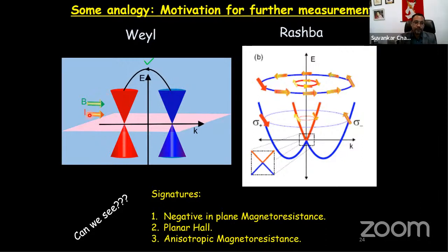And when you change the angle between the current direction and magnetic field, the magnetoresistance amount changes similarly. Now, if you think of Rashba, I don't want to say they are exactly the same, but the similarity is that here also you have two types of spin chirality, but instead of having two Dirac cones, it is circulated by one Dirac cone. So the signatures of Weyl fermions, or Weyl-type signatures in transport properties, are negative in-plane magnetoresistance, planar Hall effect, and anisotropic magnetoresistance.